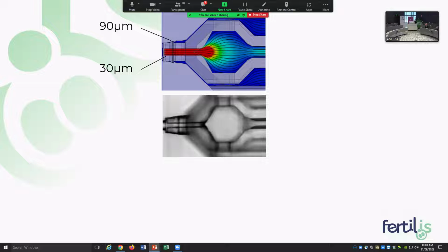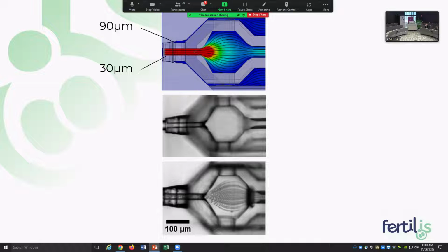We ran computational fluid dynamics simulation to work out how the flow would go through the nozzle and then fill the cavity. What we were looking for was how the distribution of flow would work. We printed these parts on the Nano One and were able to test for fitment, so how it interlocks and holds in place. And then we were also able to run a polystyrene bead to have a look at the flow. Amassing images, we were able to generate this. We were pretty happy with the alignment of what we saw experimentally with what we achieved through CFD.